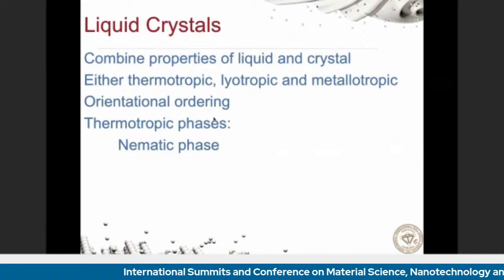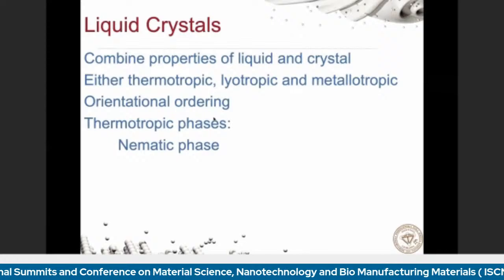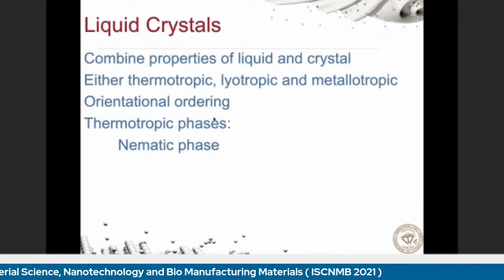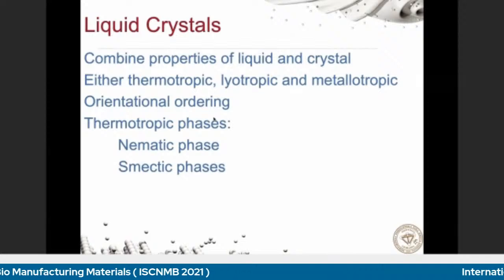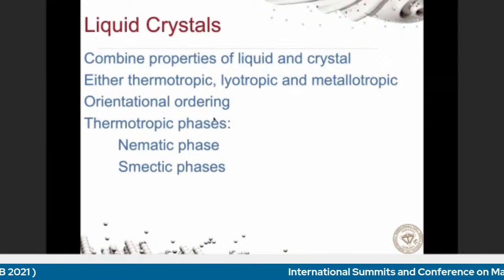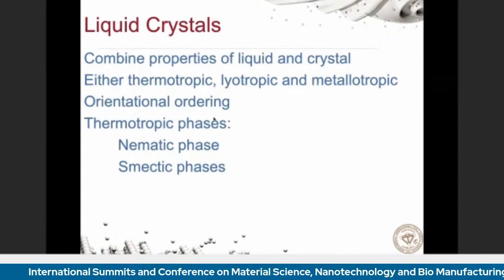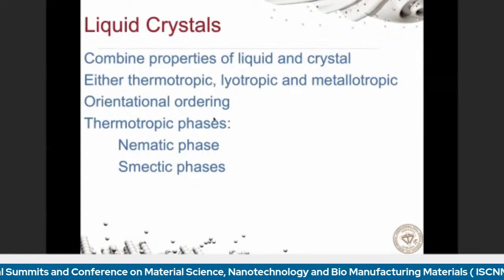We have studied this a lot with nuclear magnetic resonance, where you can really see very nicely, like deuteron NMR was the method of choice that we used a long time ago, and we could see the nematic transitions really very nicely. Smectic transition is, however, a little bit more difficult to see with nuclear magnetic resonance, for example, from coupling between nematic and smectic phase. However, if you want to see it better, then you go to other methods like X-rays.